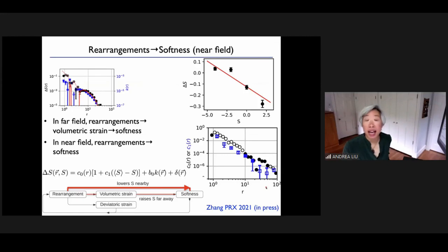All right, what happens closer? Well, it turns out that the change of softness depends on the softness of the particle. How much its softness changes depends on its own softness. And in fact, it has this form. It looks like this. The change of softness has a piece which depends on how different the softness is from the average softness, from the mean softness, okay? As well as a piece which is just a constant here.